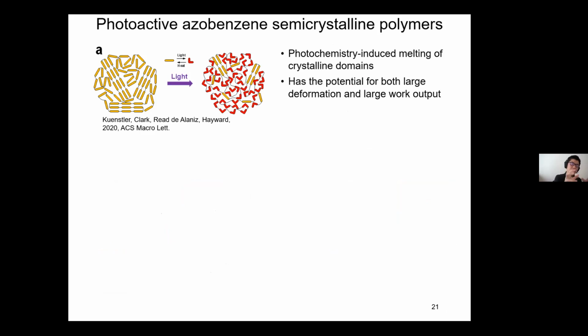So let's move on to use this kind of concept on another material, which is this photoactive semicrystalline polymer. This idea really comes from another collaborator, Professor Ryan Hayward. What they proposed and did in experiment is, now, if I have these molecules cross-linked, polymerized by azobenzene, okay? And then this trans-azobenzene can form crystals, as we saw before. But now in the polymer, they really form this semicrystalline structure.